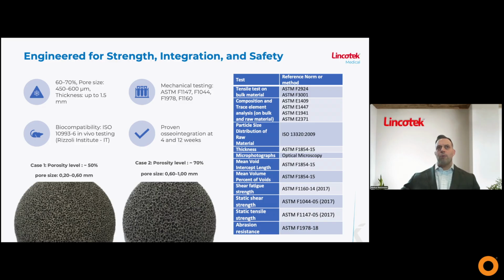From a technical standpoint, bone pore isn't just a one-size-fits-all lattice. It has been deliberately engineered and validated across two distinct porosity configurations. The first one is in a range of 50% porosity with a pore size of 0.2 to 0.6 millimeter. And the second one, the upper limit, is in a range of 70% porosity with a pore size of 0.6 to 1 millimeter. These specific ranges were not chosen arbitrarily. They are a result of mechanical testing, trace element and composition analysis, particle size distributions, and biocompatibility testing in the end.